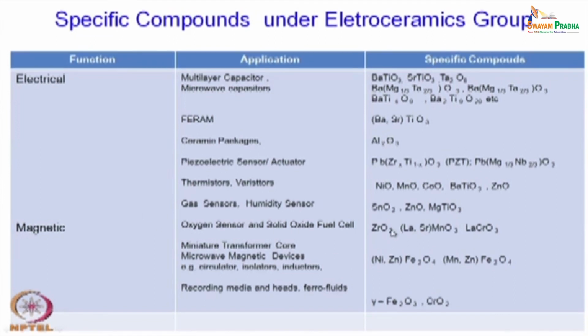You can make oxygen concentration cells or electrochemical cells using some of the solid oxides, particularly zirconium dioxide. Zirconium dioxide has a very interesting property. PSZ, partially stabilized zirconia, is a tough ceramic material, while stabilized zirconia, fully stabilized with some calcium oxide or yttrium oxide addition, enhances the oxygen ion conductivity. So, it is no longer an electronic conductor, but an oxygen ion conductor.